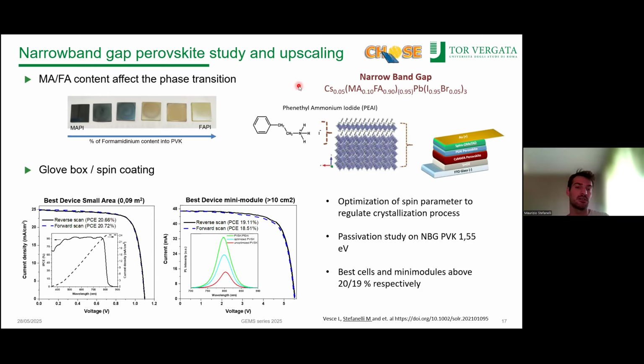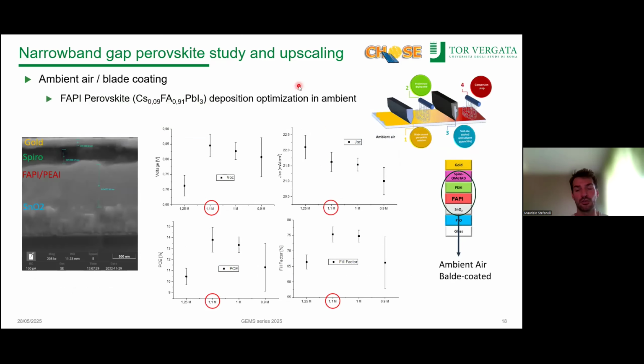So once we got the good results in the glovebox, it's time to move to ambient air, where we use blade coating, not spin coating. In this case, the stoichiometry of the formulation is a little bit changed. We increase the cesium content, which can act as a seeding site and help the crystallization in the blade coating technique. And we avoid methylammonium in general, using it only as an additive, as usual, like methylammonium chloride.